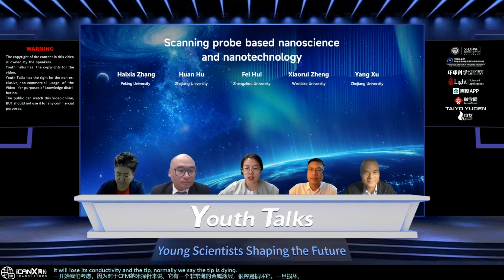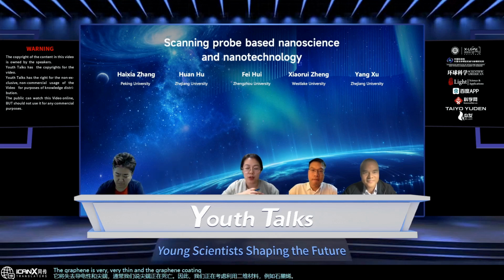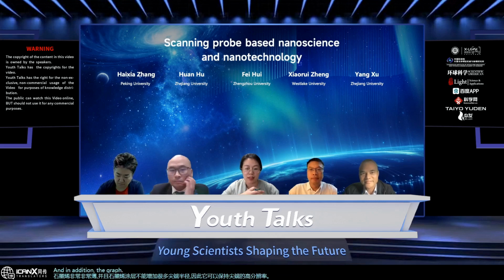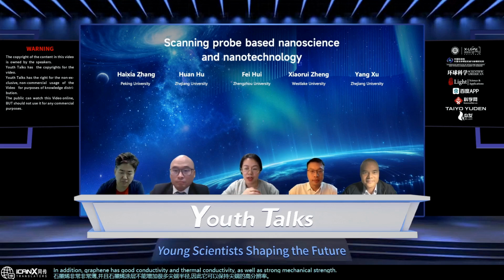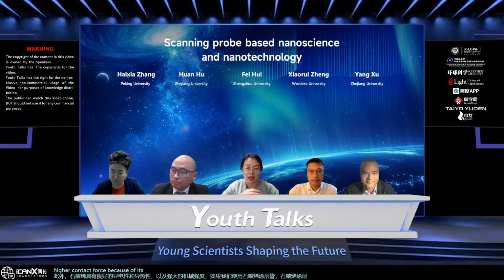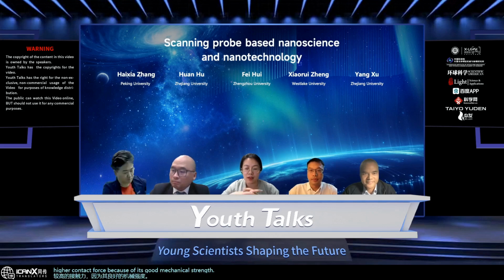So we are considering taking advantage of two-dimensional materials, for example, graphene. The graphene is very, very thin, and the graphene coating cannot increase the tip radius much, so it can keep the high resolution of the tip. In addition, the graphene has good conductivity and thermal conductivity, as well as strong mechanical strength. The graphene coated tip can bear a higher contact force because of its good mechanical strength, and the other issue that causes damage to the C-AFM tip is the high current density.